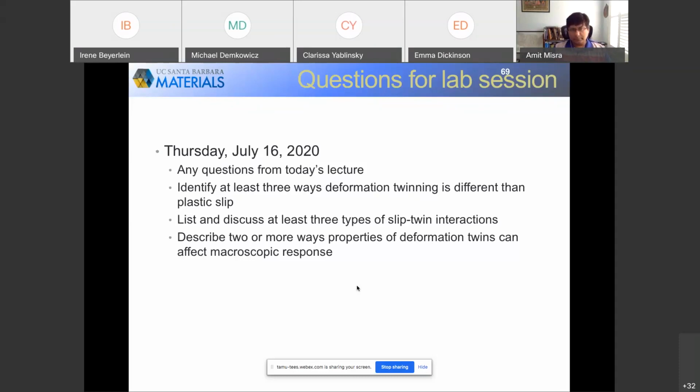this would be a poor boundary for nucleating twins, because it doesn't have any triggering or initiating large defect in which a twin can form. A highly defective grain boundary, on the other hand, would be ideal for nucleating twins.